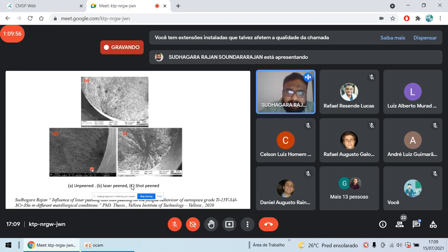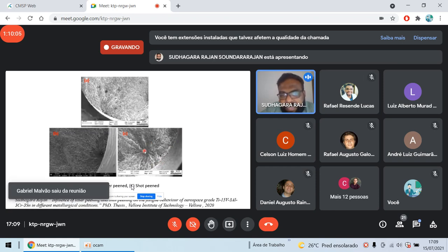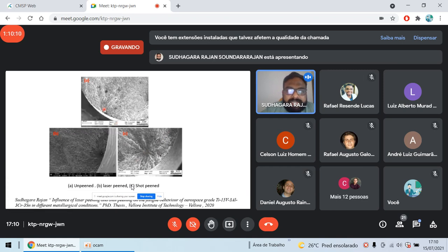So here you can find the crack initiation in this subsurface region, because the surface has a compressive residual stress due to the shot peening. So here the crack initiates and it grows. This is how the crack initiates in the surface.